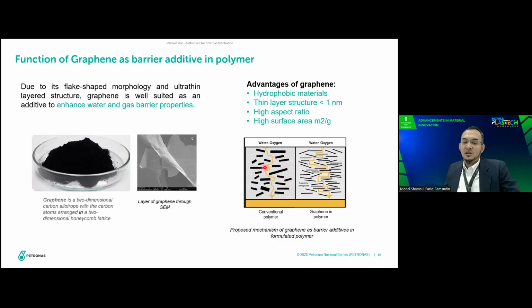As an example here, if we take silica or glass flake, some of the sizes are at the micron level, so they also can give barrier performance. But when we add graphene, it will further improve the tortuosity, where it will slow down the gas or water penetrating from the substrate, the HDPE film, to the product or to the main substrate that contacts the polymer. So this is the beauty of graphene, the function of graphene as a barrier. It will further slow down the diffusion of gas or oxygen.